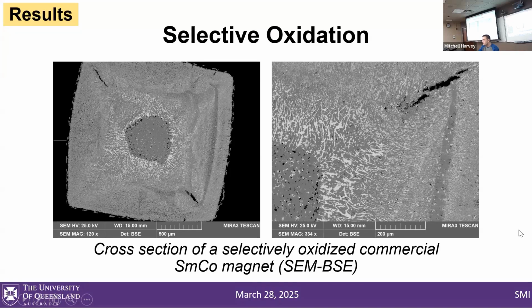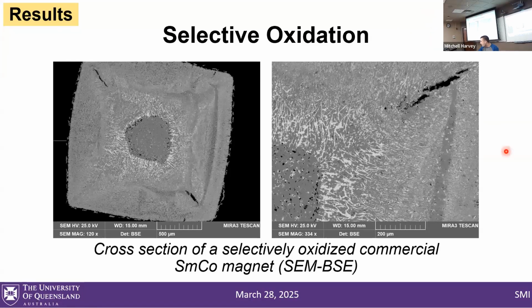And we get a very interesting oxide microstructure. At the edge, the oxide microstructure is very fine, and as you progress toward the interior, it gets very, very coarse. Part of the work we're trying to do is optimize this microstructure, trying to get this very coarse oxide, because the fine one is very difficult to separate. These oxide particles are maybe 1 to 10 microns, and these are 10 to 50 microns, depending on how you measure them.